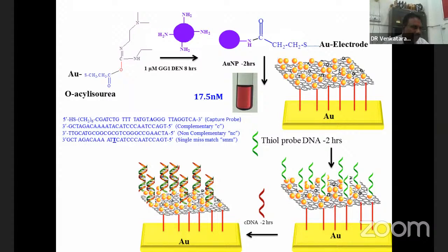For that purpose, the combination of graphene and gold nanoparticle were taken together on a gold electrode, because we don't want to have a physical absorption of graphene on the gold surface. Rather, we also want stability of the layer, so we put the intermediate molecular layer between these two, and on top of which we put a DNA capture probe, and then the target probe. We form a helical formation.